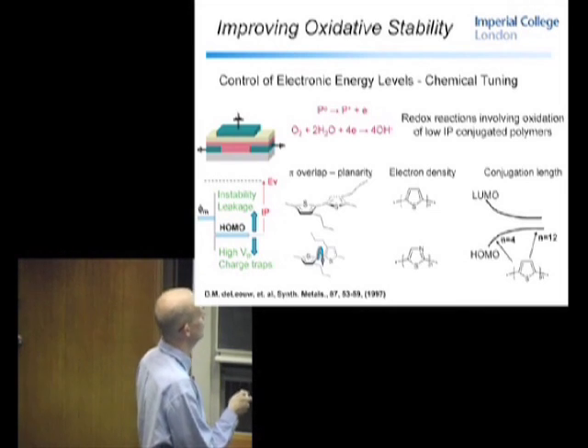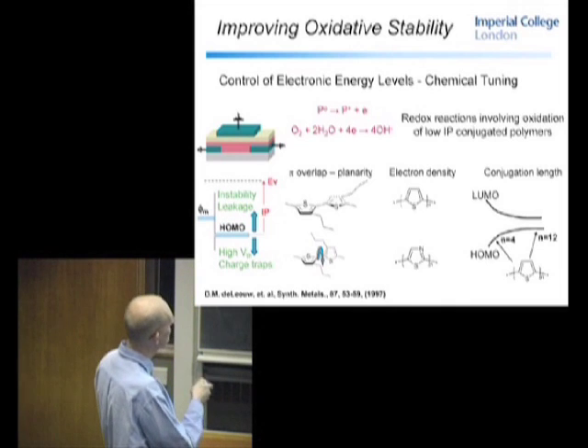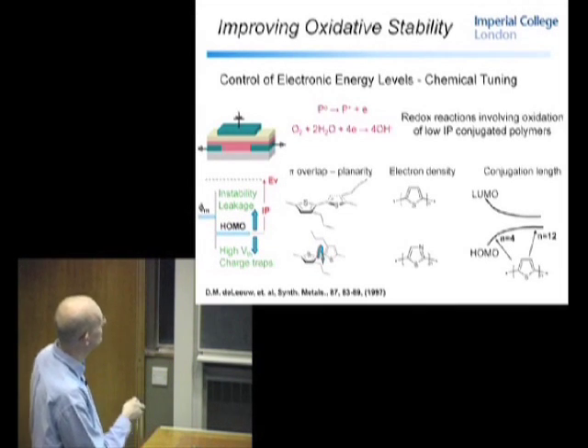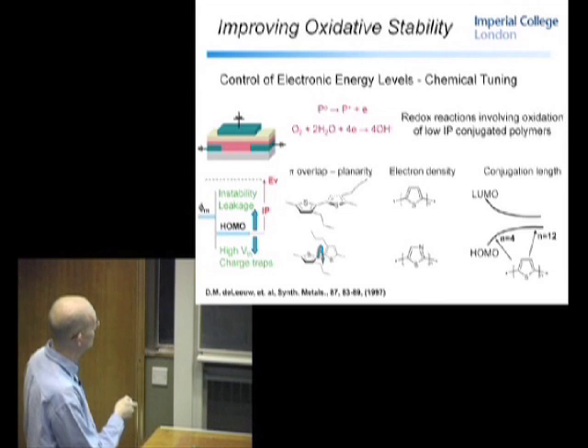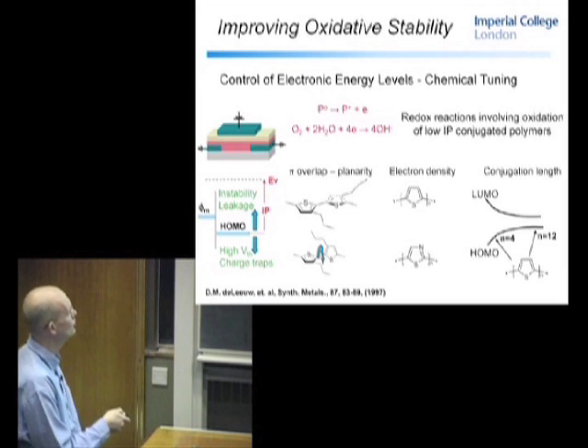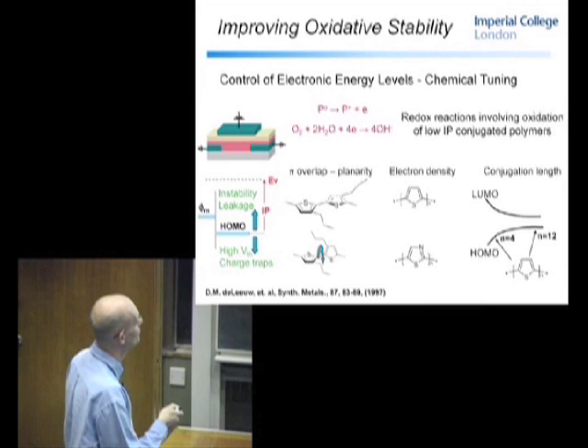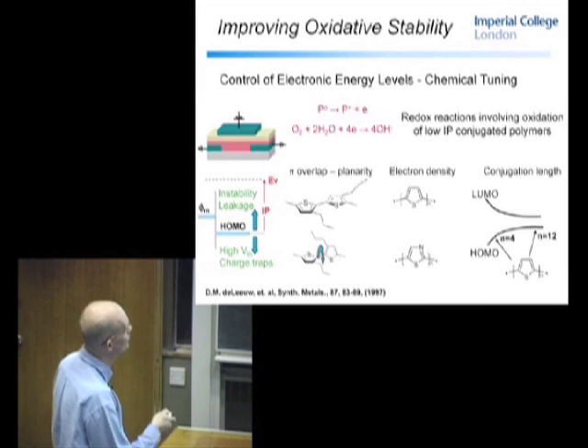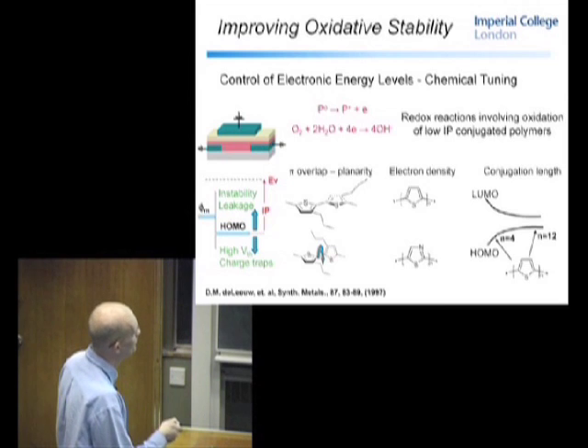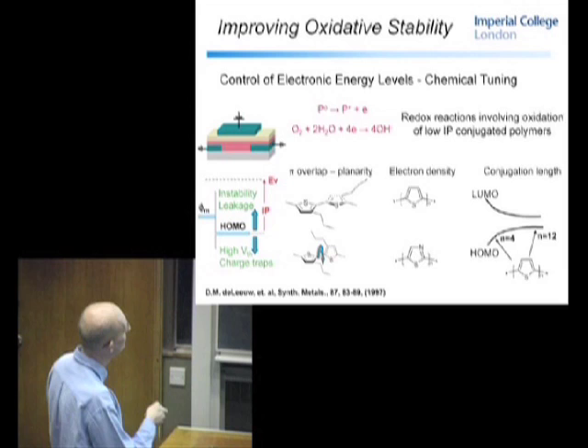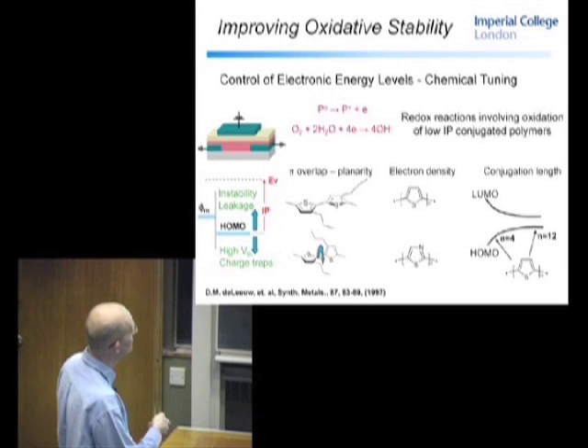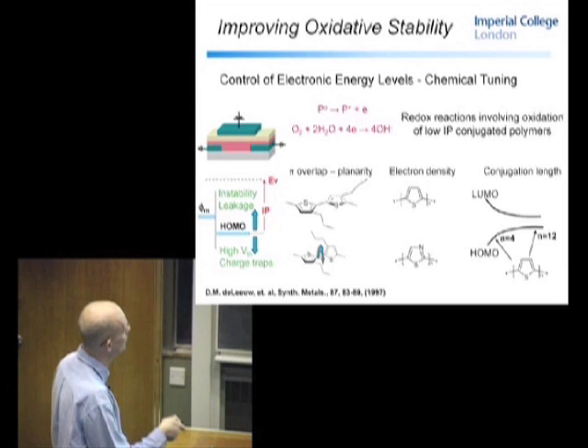So what can we do to push this ionization potential? If you just look at the energy diagram here, the ionization potential is defined as the energy of the HOMO subtracted from the vacuum energy. So if you want a lower lying HOMO energy level, then there are some tricks as chemists you can do. And I guess this is a physics department, so I won't go into this in too much detail, but you can play around with conformations to stop the intramolecular pi orbital overlap. You can change the electron density of the backbone. You can change the conjugation length, and you can play around here. And there's a nice paper by the Philips group that shows why this is important.